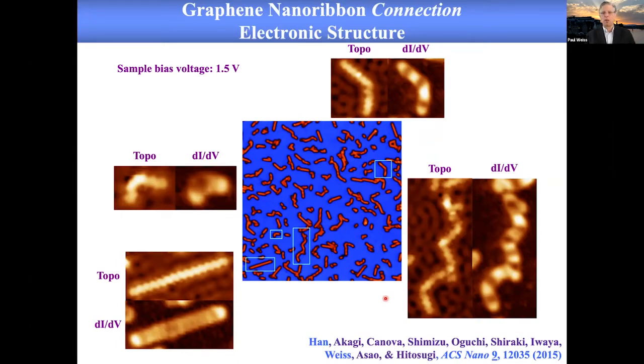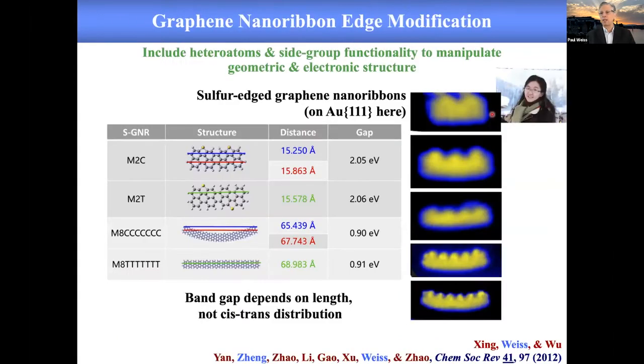In the meantime, we can also functionalize the sides of the graphene nanoribbons. This is work of Ling Bojing, a joint student I had with Kai Wu in Beijing, who showed that these sulfur functionalized graphene nanoribbons have band gaps that really only depend upon the length, and the sulfur can be in this cis or trans form, but that doesn't affect electronic properties.